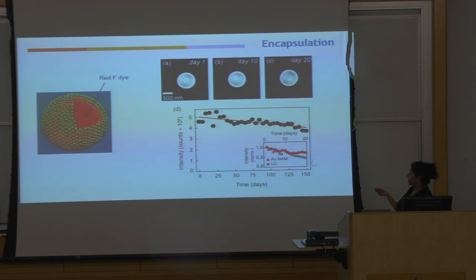We even did some control measurements that said the decrease in intensity could actually be not leakage, but dyes just bleach with time. Their emission intensity goes down with time, so it could even be partly that. So this shell with a non-solid wall can encapsulate dyes. We tried this with the cancer drug Taxol for 5 months, longer than most systems can encapsulate a foreign object.